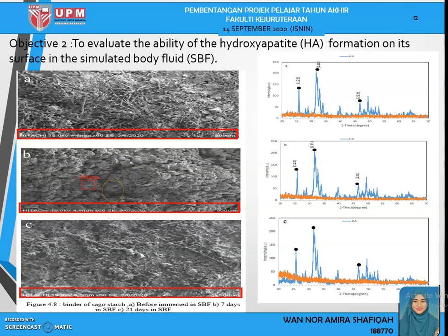particles were bonded together. There are various grains of uniform shape and size on the surface of the samples. It's clearly observed that hydroxyapatite layers are formed. For figure C, it shows that from the 7 days, the thickness of hydroxyapatite increased after 21 days immersed in the SBF.